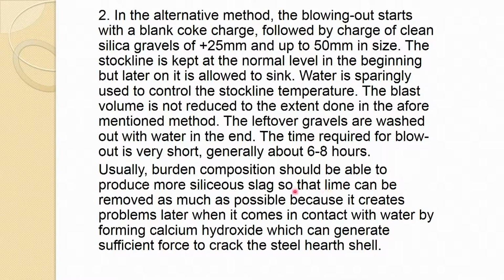So, that lime can be removed as much as possible, because it creates problems later when it comes in contact with water, forming calcium hydroxide, which can generate sufficient force to crack the steel hearth shell. So, essentially why we are saying more siliceous slag, we really do not want to have any lime in this slag, because when you put the water in this, calcium oxide with water gives you calcium hydroxide,